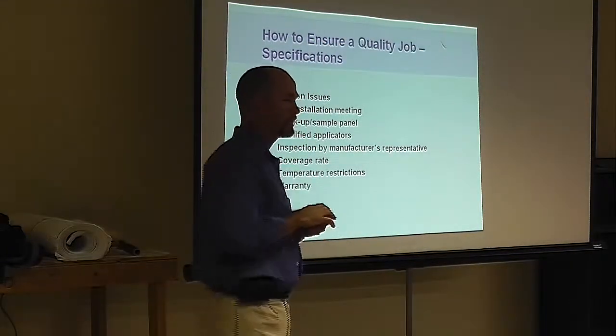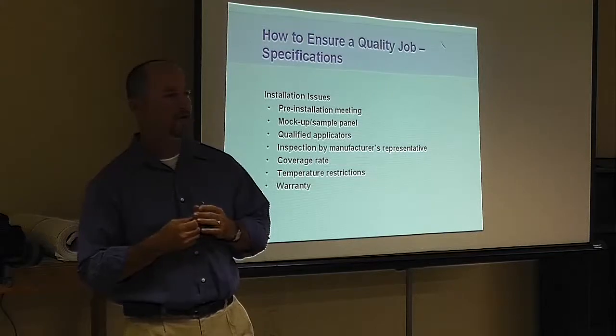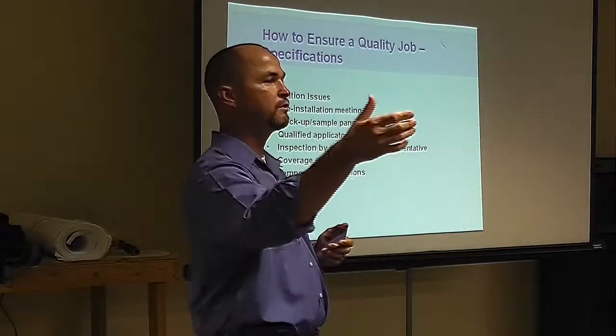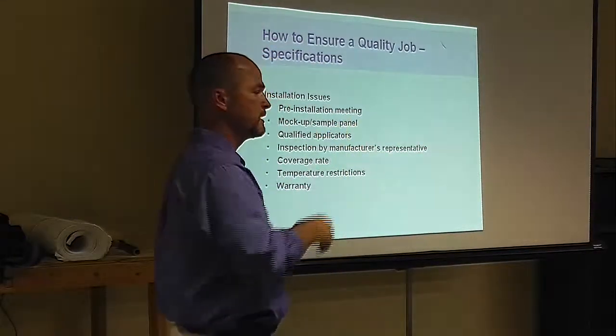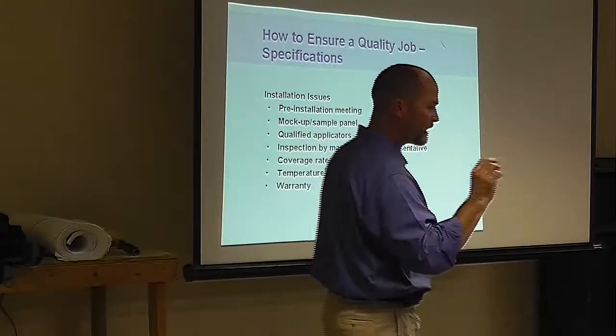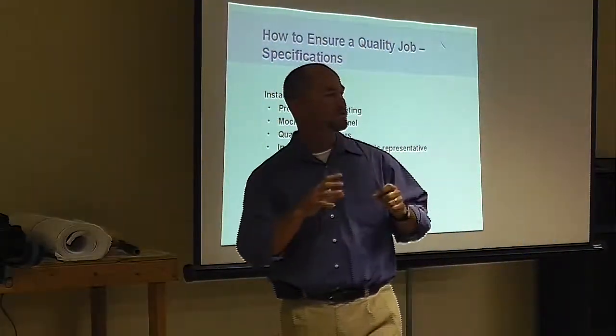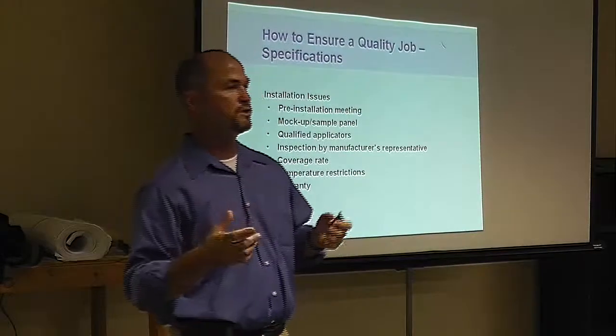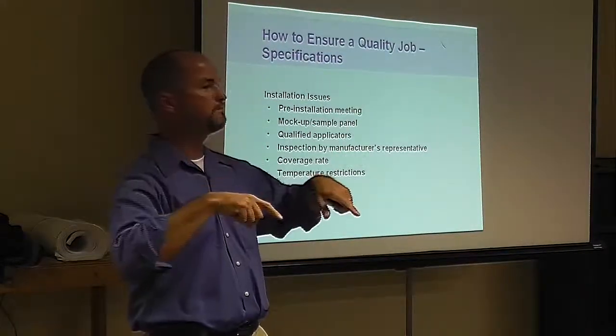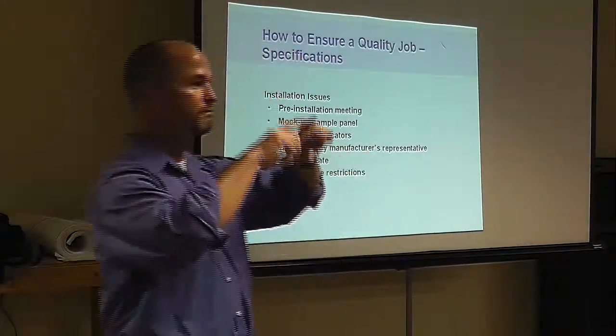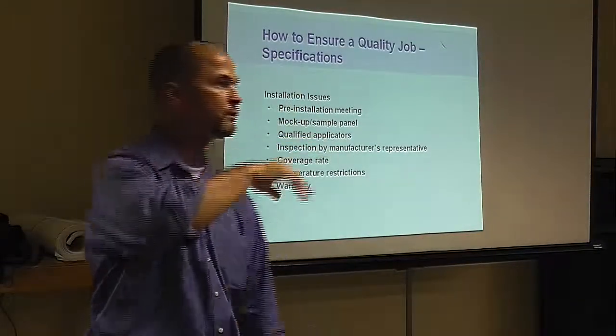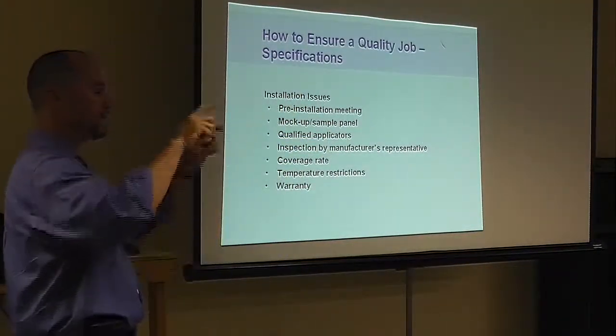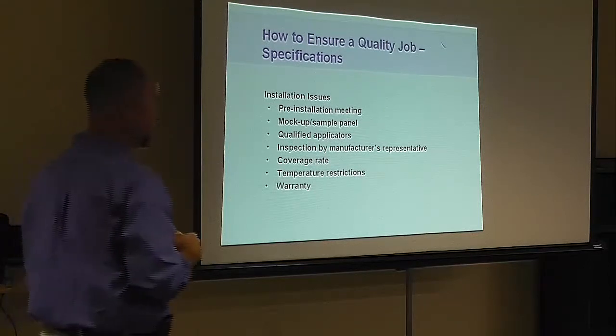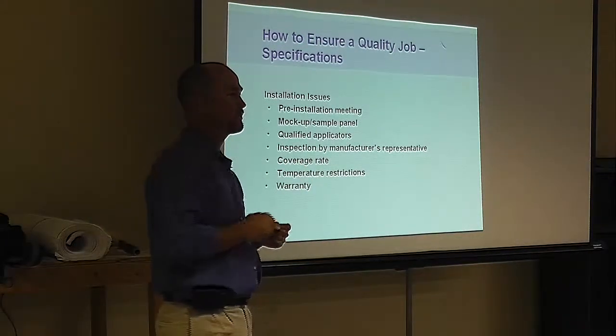If you've got a product that's basically 50% solids and it goes on at 20 mils wet, it's going to dry at about 10 mils dry. And you can only use wet mil gauges on smooth substrates. There's no way to check it on a real rough substrate to see if you got the proper mil thickness. What you have to do is a takeoff. Figure 100 square feet. A gallon should go about 100 square feet on one substrate. Now if it's real rough, you need to take that down because you need to take into consideration the corrugation and everything to it. So figure that area about 60 square feet.